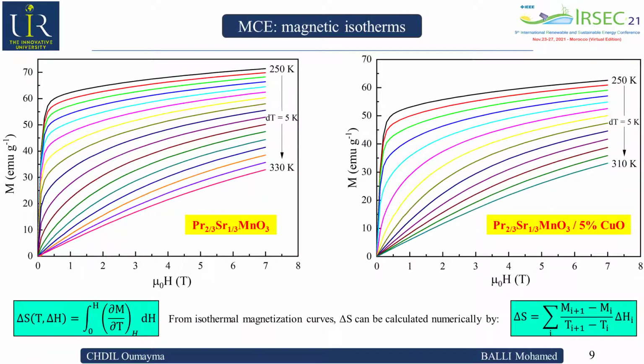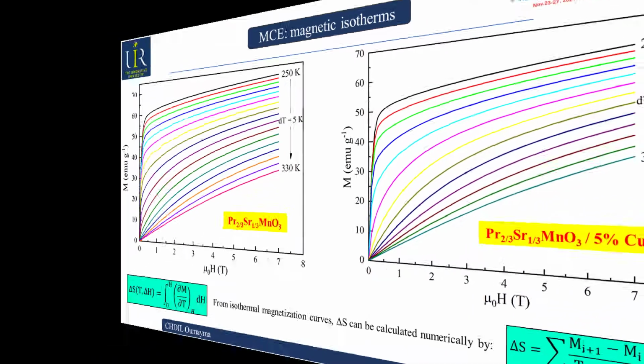And here, based on the measured magnetization curves, we can observe that below the Curie temperature, the magnetization curves exhibit non-linear patterns with a tendency to saturate in the presence of magnetic fields, indicating a ferromagnetic property. However, above the Curie temperature, the magnetization evolves almost linearly, indicating a paramagnetic state caused by the thermal agitation of the magnetic moments. Moreover, based on these results, the magnetic entropy change caused by the variation of the magnetic field can be determined using the well-known Maxwell relations.